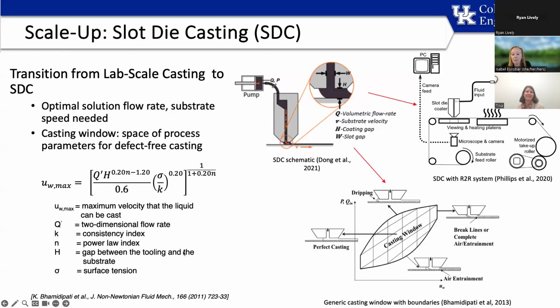And if we are over here in the bottom where the velocity is too high, but the flow rate of the dope is not high enough, we have some air entrapment. So we're going to have a lot of bubbles, very large bubbles within the membrane that could potentially explode or collapse during filtration.